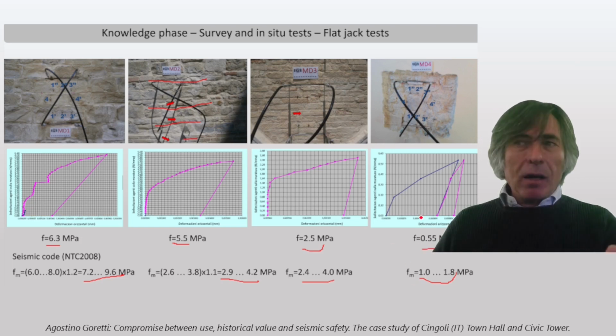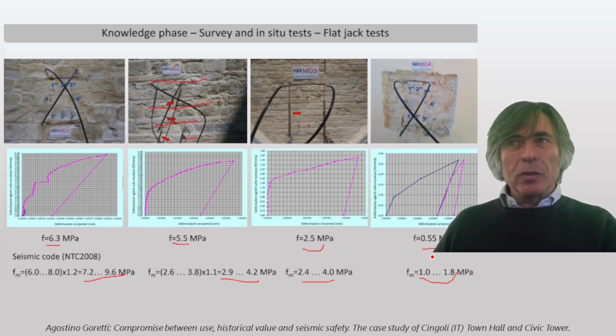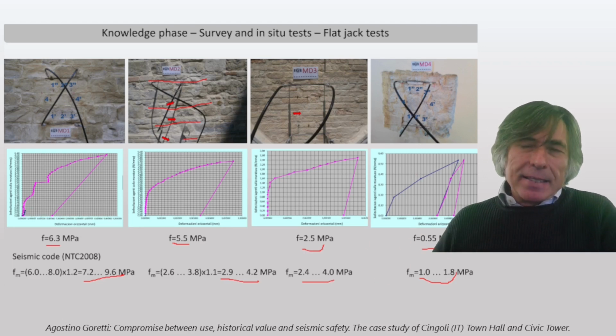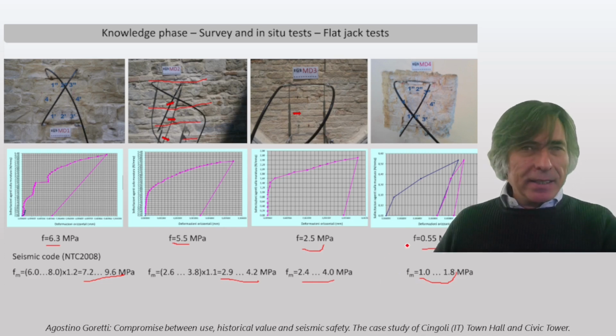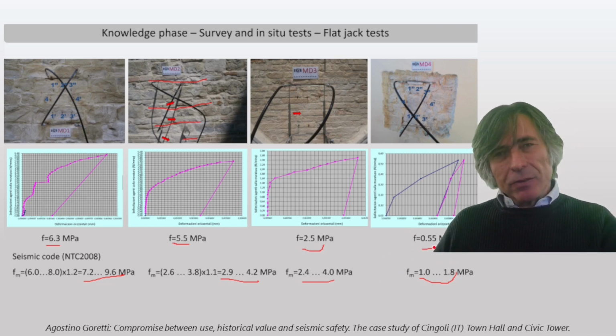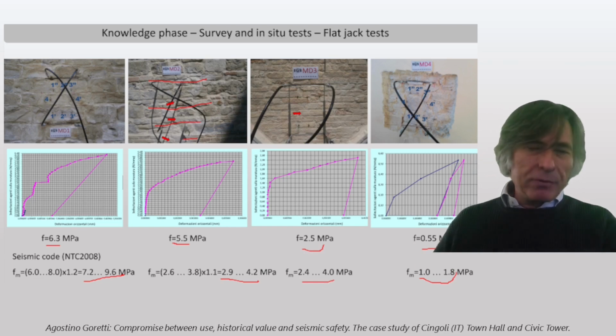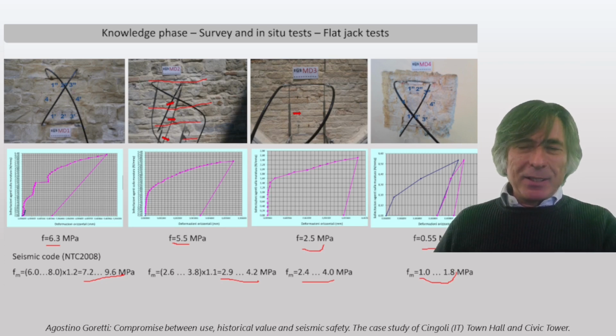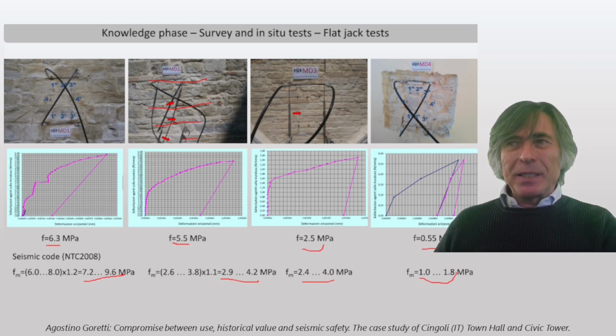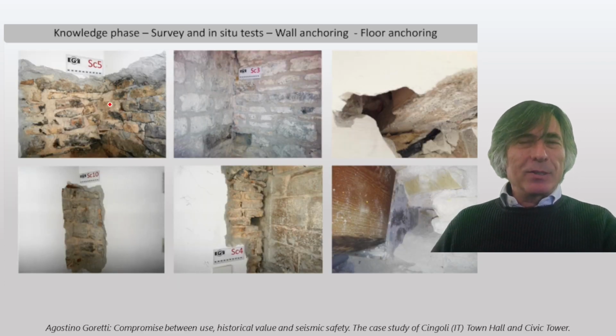So somehow we, as engineers, don't have to be so strict with this number, even if I understand that the authorities in charge of control usually are very strict, and they say if you got 0.5 you have to use 0.5. This is a very questionable, debatable issue, and I don't fully agree with this if you make some interpretation, but nevertheless this is the value that has been used in the calculation as well.